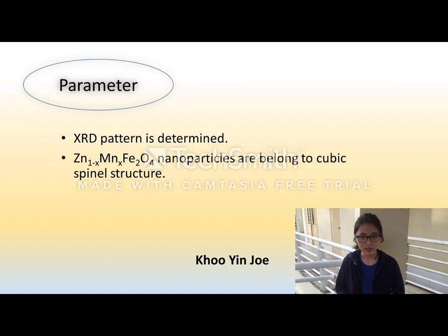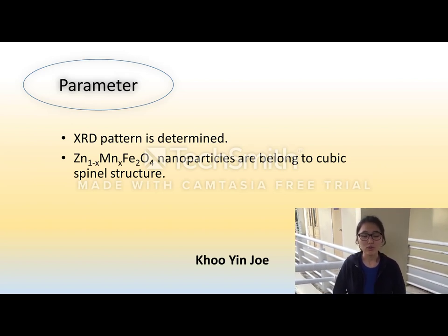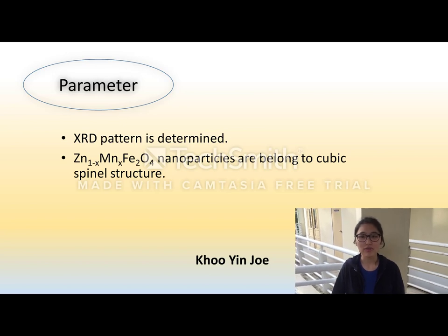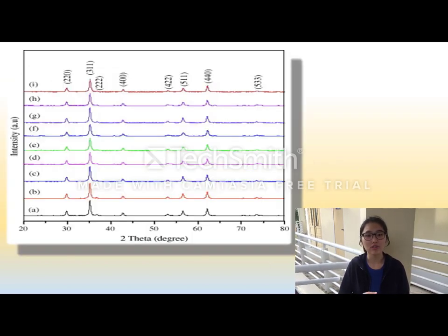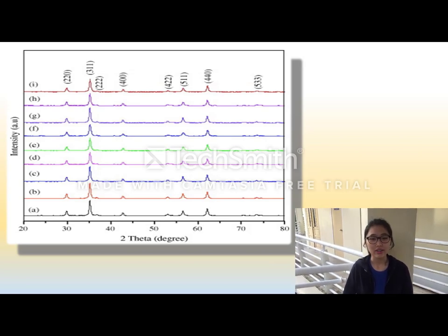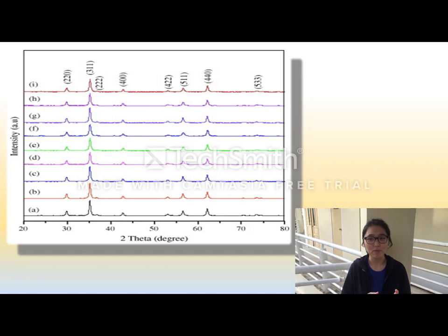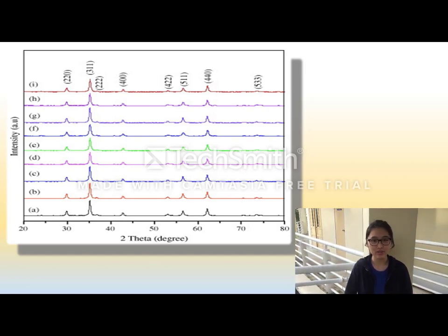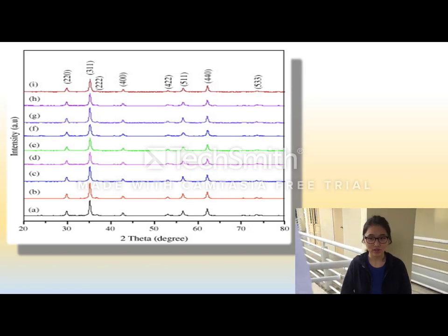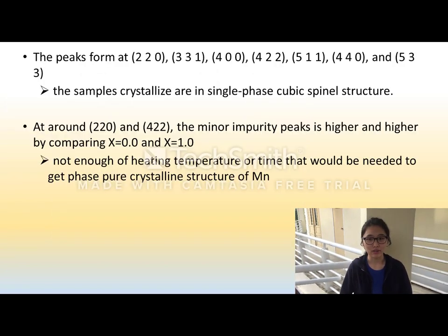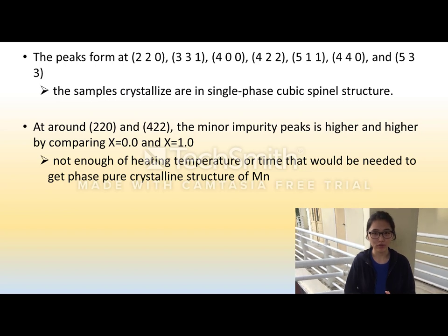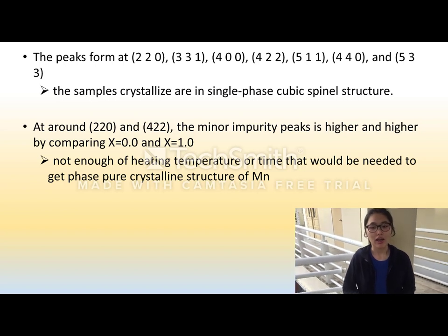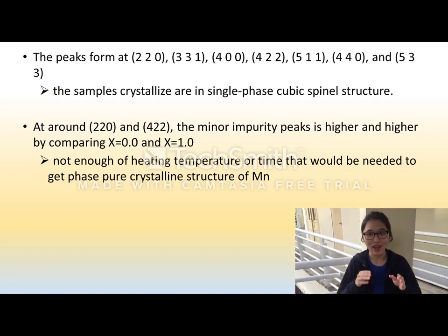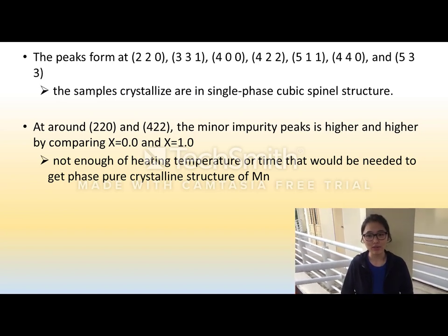Hello everyone, thank you to my group mate, and now I will talk about the parameters and how they changed in the nanocrystal. From the graph of intensity against 2 theta in degrees, we know that Zn 1 minus x Mn x Fe2O4 nanoparticles have a cubic spinel structure. And from the XRD pattern, at around the 220, 331, 400, 422, 511, 440, and 533 planes, we can indicate that the sample crystalline is in a single phase